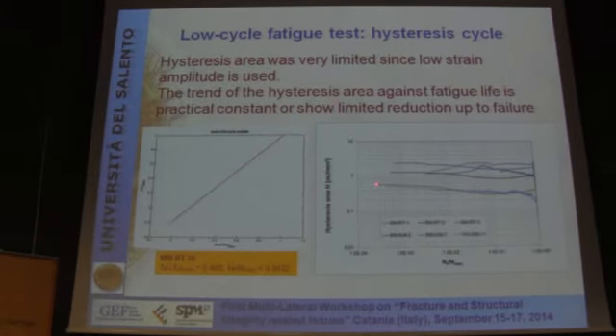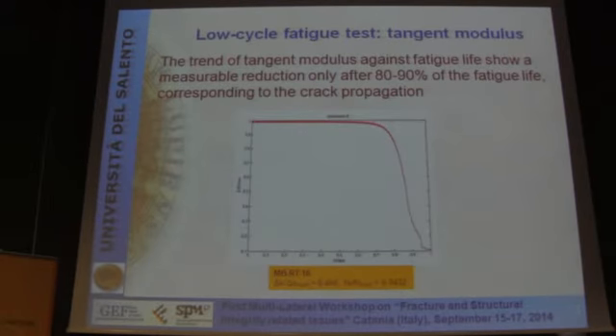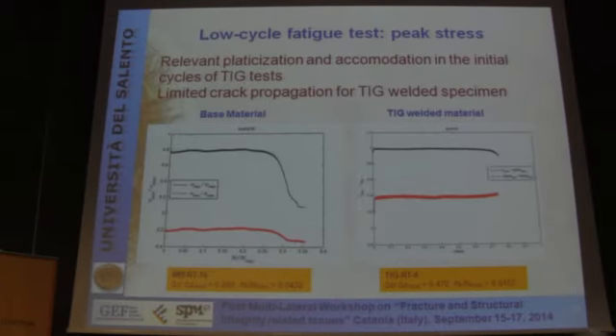Only in a few cases is it possible to consider the trend of hysteresis area against the fatigue life, and this trend was almost constant, both for base material and TIG welded material. Another trend that we can consider is the change of the tangent modulus. This is a typical trend, and we can measure a reduction of tangent modulus only when a crack is propagating. So it is not useful during the crack initiation phase.